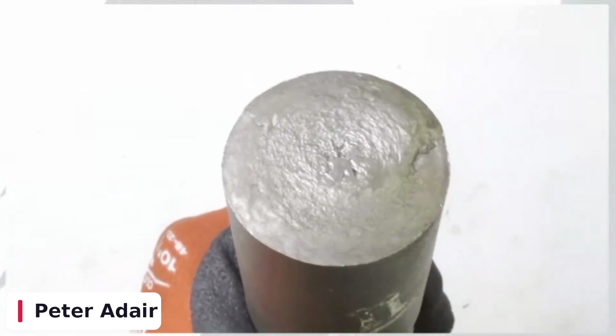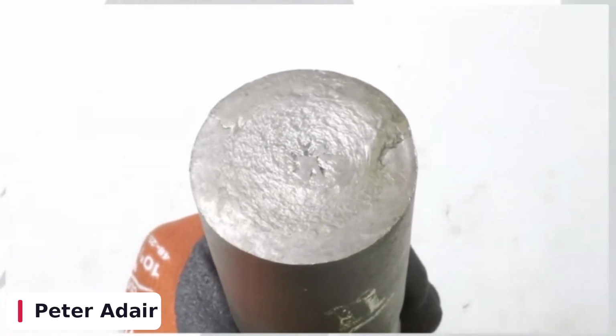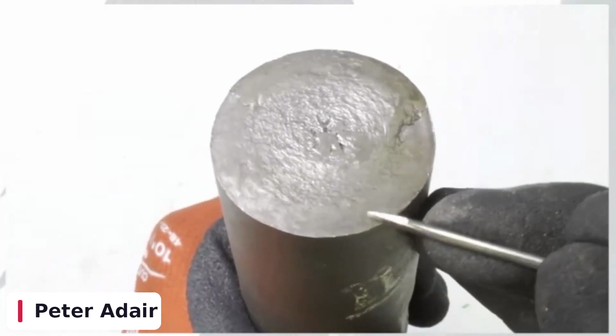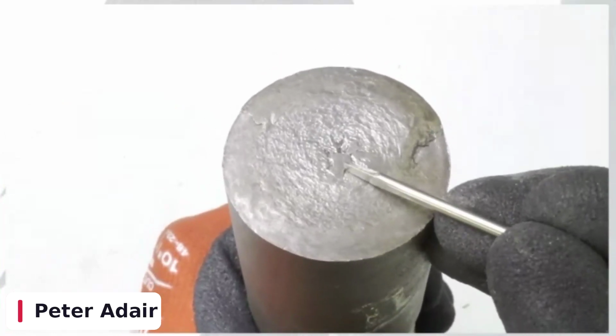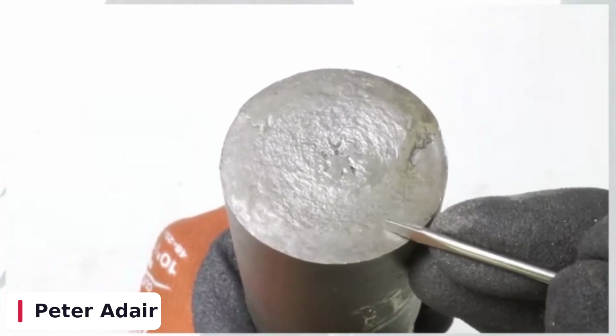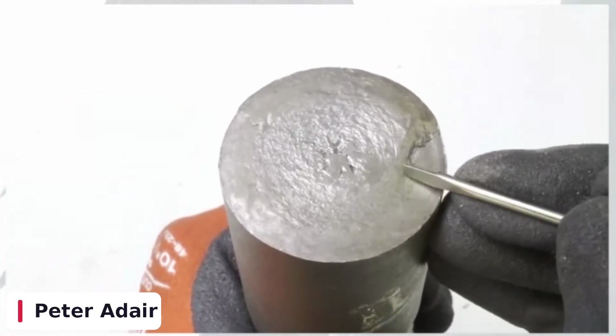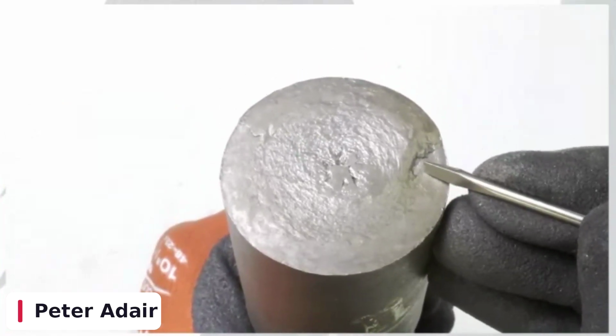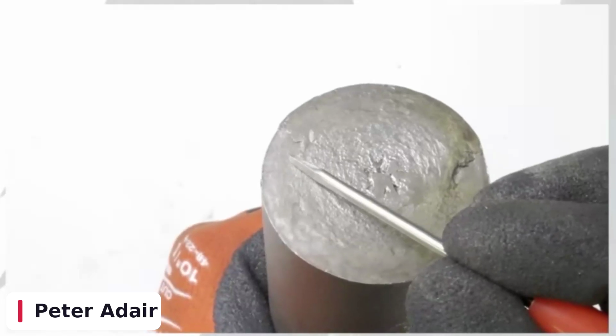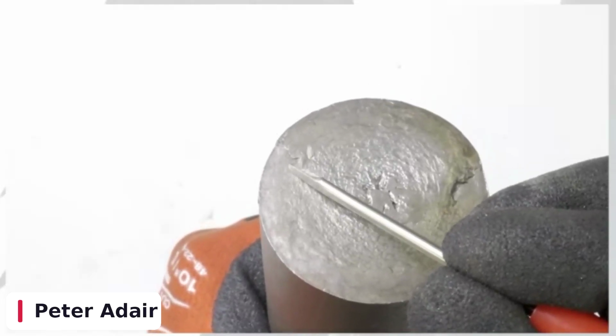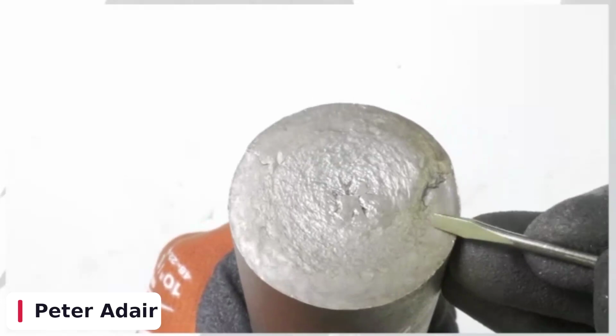But if I look at this, I'm going to do my best. It ran for a while on the other half of it, but we can see out here I got a fine grain structure and a coarse grain structure. So I know I have a heat treat hardened shell, and you can see my ratchet mark right here. So this is where it started, and it looks like I got another one over here where it finished the break off. So I have two origins. This is probably my original right here where it originally hit.